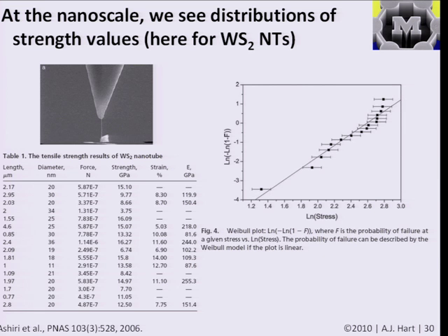And here, they're able to plot out, in a relatively organized fashion, a distribution in the probability of failure as a function of the applied stress. So F, the failure probability, is basically the probability that the material will fail at a stress equal to or less than the applied stress. If you choose a stress which is really high, and it's going to make all the materials fail, then your probability of failure is 1. If you choose a lower stress, then your probability of failure might be 1/2. Formally, this plot is what's called a Weibull plot. Perhaps from undergraduate mechanics you remember Weibull statistics, and they fit the Weibull relationship, which is a line when you plot the axes between F and stress, and see that it's a pretty good representation.